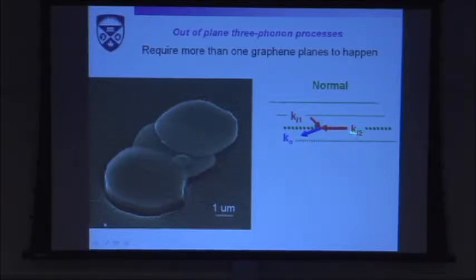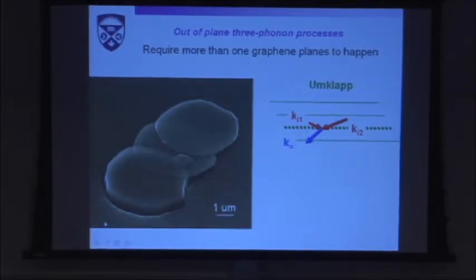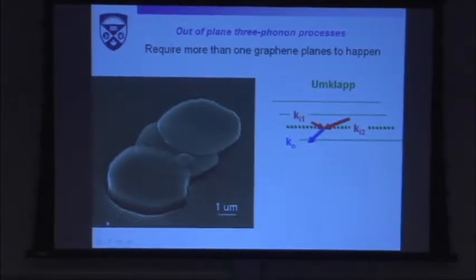And in that case, again, you see, this is one layer of graphene. You have other layers. In the K space, the reciprocal space, it is basically the same. And you can have normal processes or umklapp processes. Basically, the phonon excitation is scattered from one plane to another. These are really the processes that limit the thermal conductivity of graphite. That is incidentally pretty good. Graphite is a material for thermal management applications. You coat pistons with graphite-like carbon or with graphite to evacuate heat better in cars.